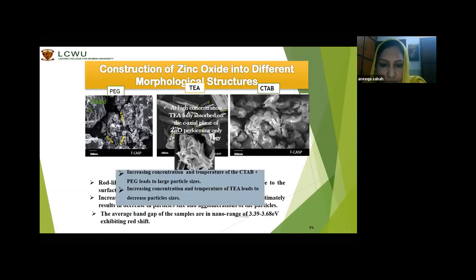Increasing concentration and temperature of CTAB and PEG leads to larger particle size, while increasing concentration and temperature of TEA leads to a decrease in particle size. So by differentiating concentration and temperature, we get different sizes.